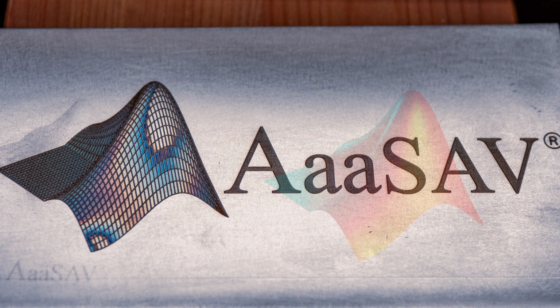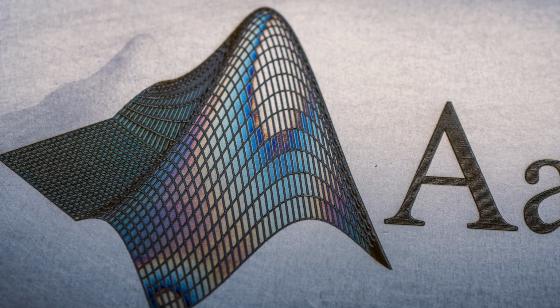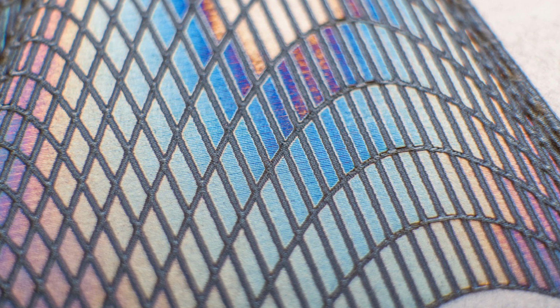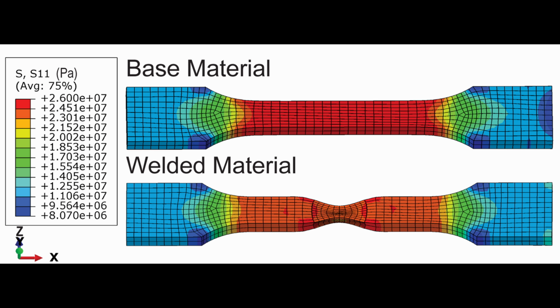scrap stainless steel. All of the metal that I've been using up until now has been 0.7mm thick to try and save on the cost, but this piece is 3mm thick and notice how it doesn't warp at all while I'm using the laser on it. It is a pretty random thing to make, but I was really pleased with the way that the design and the colours came out on this one. I thought that the range of colours was really nice and the actual engraving itself was very crisp. I imagine that this type of engraving would be really cool for printing out FEA results on big sheets of stainless steel, if you had some cool results that you wanted to make into a poster.